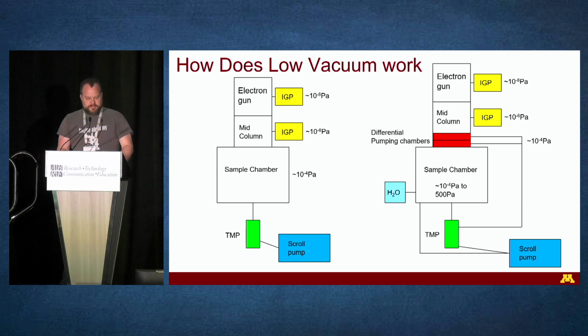With a low vacuum SEM on the right, there's a couple of extra chambers at the bottom of the column. These are differential pumping chambers. They enable you to maintain the ultra-high vacuum in the column so that the electron gun keeps working whilst maintaining a relatively high pressure in the sample chamber. In the case of our SEM, anywhere from 10 to the minus 4 up to 500 pascals of water vapor.